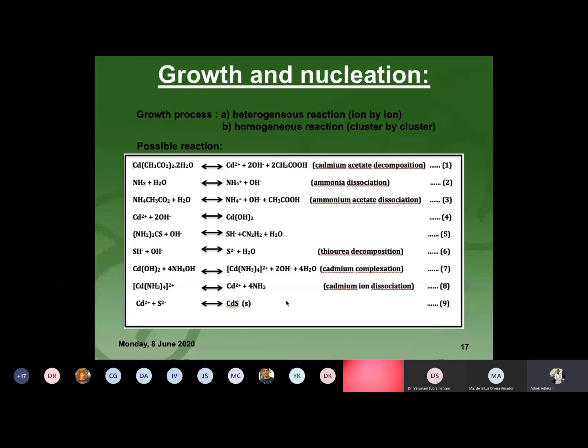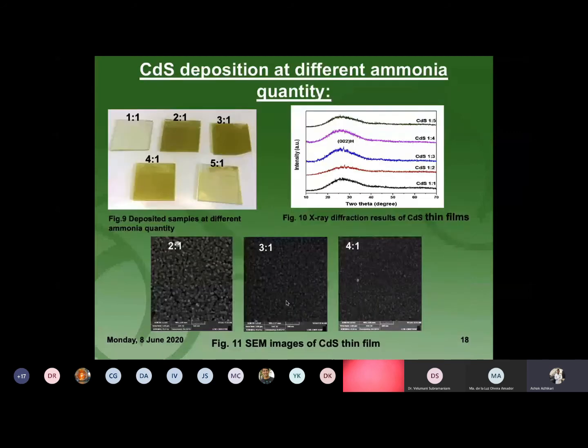I have deposited cadmium sulfide using different ammonium quantity ratios, from 1:1 to 5:1. We can see that at 1:1 there is almost no deposition occurring.